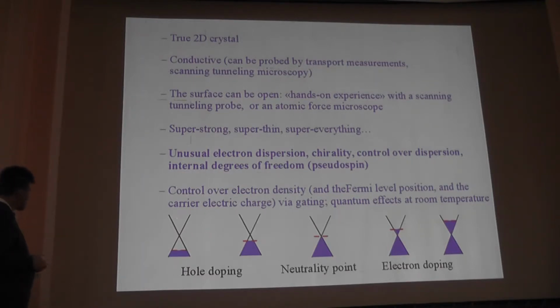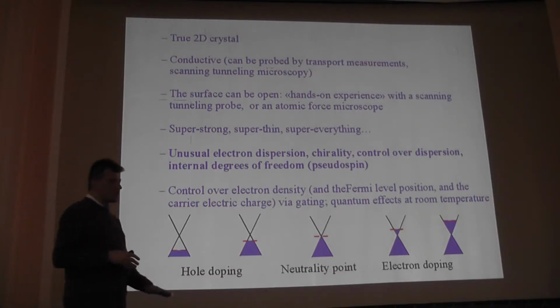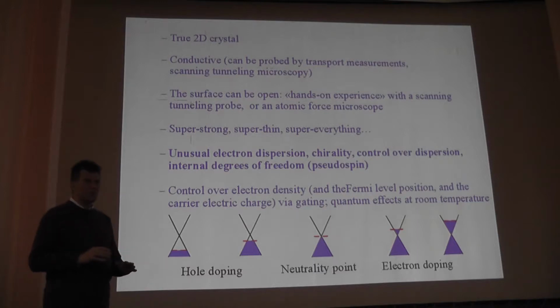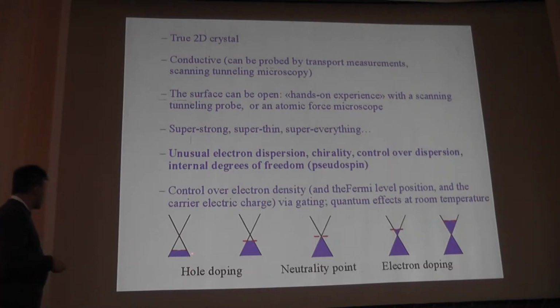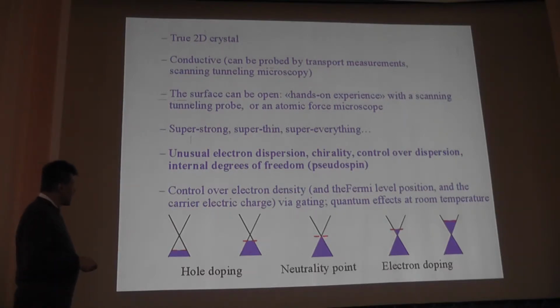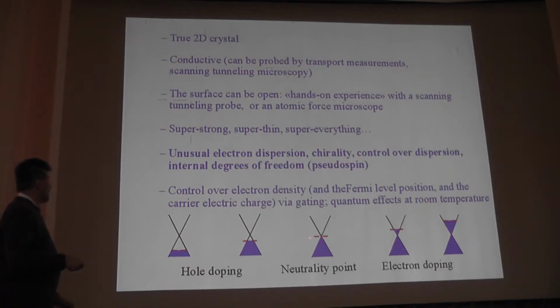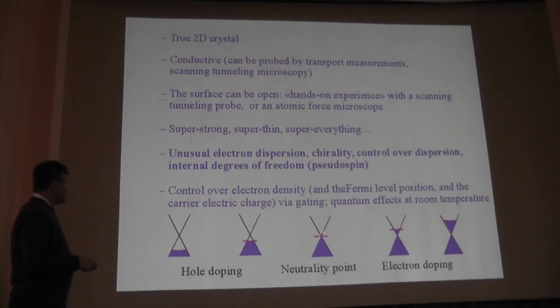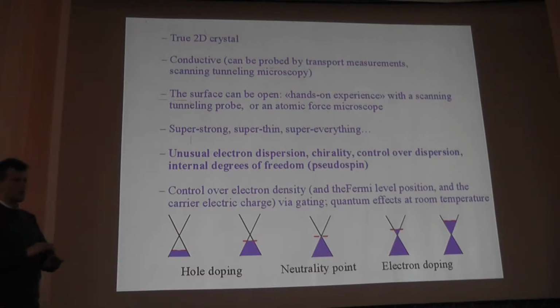And one other thing is that in graphene you can adjust the position of the Fermi level. In normal, traditional three-dimensional solids, you have to live with the Fermi level that nature provides for you, which comes out of the electron density. In graphene, you can move the position of the Fermi level. Normally, undoped graphene would give you the position of the Fermi level exactly at the conic point. But if you apply gating to the sample, you could either move the Fermi level down and even more down, or you can move it up. So you can change between the neutrality point, electron doping, and hole doping, and you can do it smoothly. So you can look at how the properties change as you go from electrons to holes.